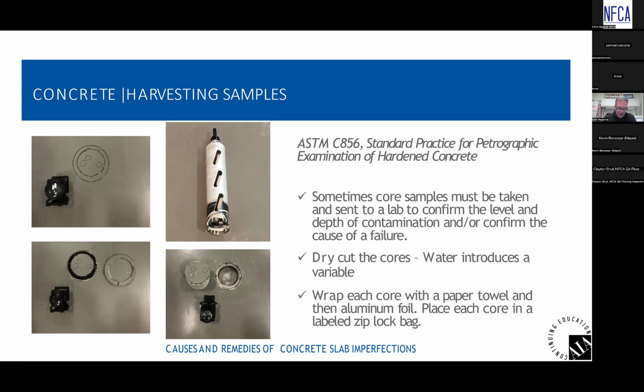The other critical piece is not wet coring. It's a dry core. Water introduces a variable. Most guys that cut concrete with diamond hole saws want a wet core. And the problem is you introduce a variable. So you can certainly dry cut.